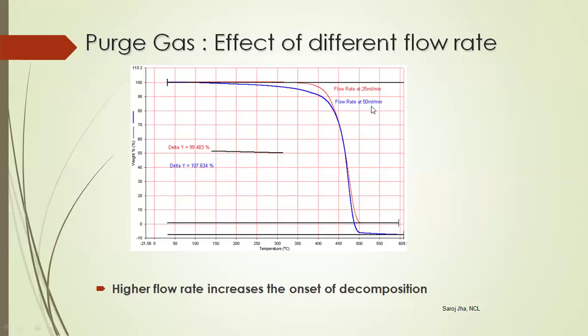Now, in a hurry or unknowingly, the next operator runs the sample at a flow rate of 50 ml per minute. Concentrate on the blue curve. See, onset of degradation had started after 150 degrees centigrade. In fact, actually at 350 degrees centigrade, nothing is happening to the sample. But because of the flow rate difference, the sample shows degradation early. Degradation pattern is different, and you are getting negative residue over here. Just see the y-axis. Your blue curve has gone below the 0% residue.